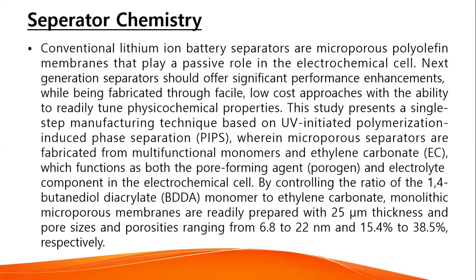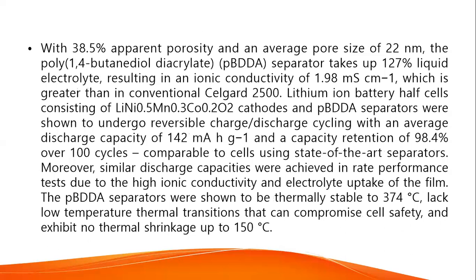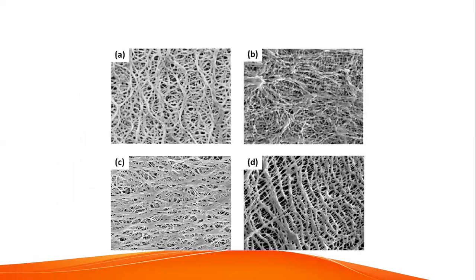By controlling the ratio of the 1,4-butanediol diacrylate monomer to ethylene carbonate, monolithic microporous membranes are readily prepared with 25 μm thickness and pore sizes and porosities ranging from 6.8 to 22 nanometers and 15.4% to 38.5% respectively, with 38.5% apparent porosity and an average pore size of 22 nanometers. The poly(1,4-butanediol diacrylate) (PBDDA) separators were shown to be thermally stable to 374 degrees centigrade, lacked low temperature thermal transitions that can compromise cell safety, and exhibit no thermal shrinkage up to 150 degrees centigrade. Here you can see the diagram.